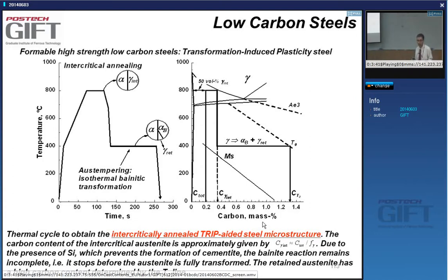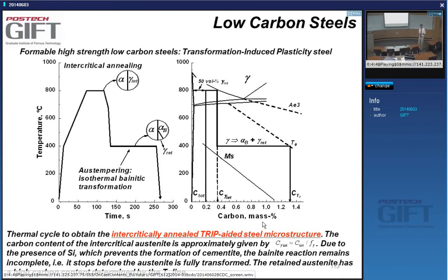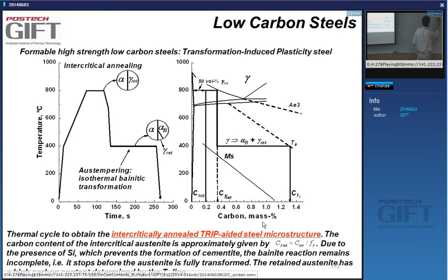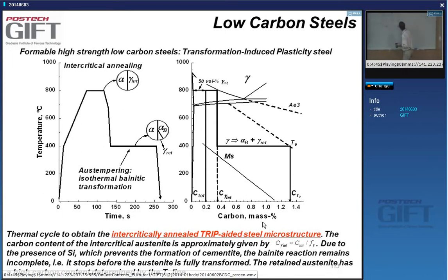The reason why there is no carbide formation is the presence of silicon. Silicon suppresses carbide formation. There are two reasons: first, silicon is not soluble in cementite, and second, silicon increases the activity of carbon in ferrite. So instead of carbide forming, the carbon content during the transformation will increase to a specific point — the T0 point — giving a carbon content of more than one percent.